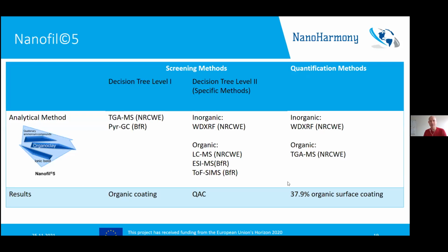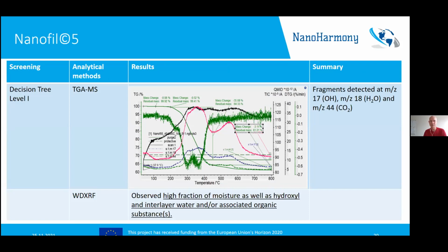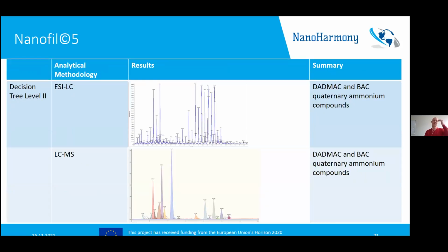Then with the organic clay, we find mass loss, and this reflects the amount of quaternary ammonium compounds coated on the nanoclay. This is also indicated by XRF, since XRF comes up with an elemental concentration, and the difference between that and 100% would yield the water content and the content of organic compounds. The actual identity of the quaternary ammonium compounds could then be identified using either direct infusion electrospray ionization LC-MS, but also normal HPLC-MS, where we separate the individual compounds and are actually also able to quantify them.